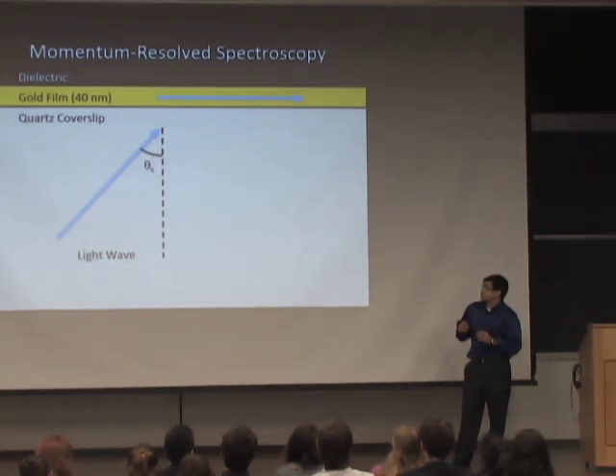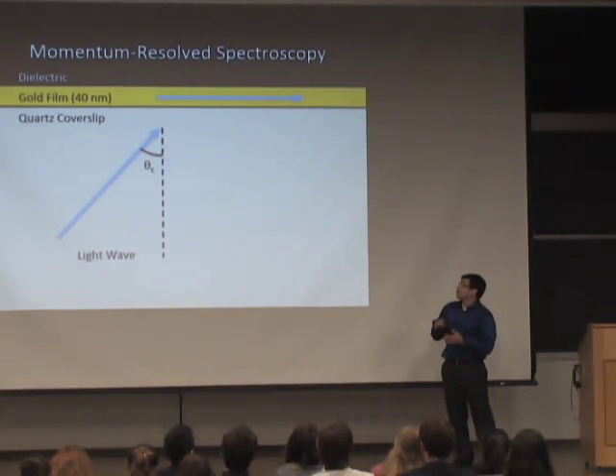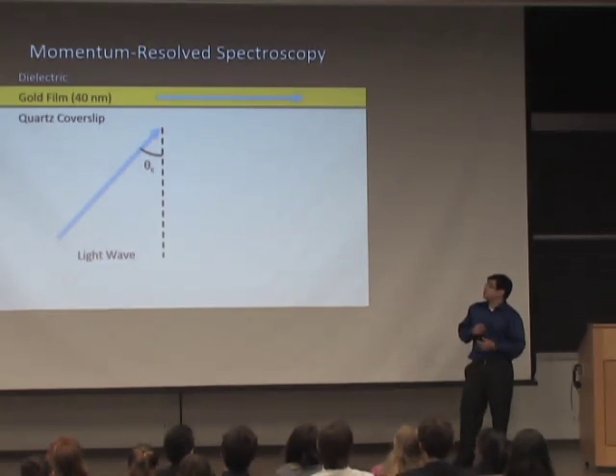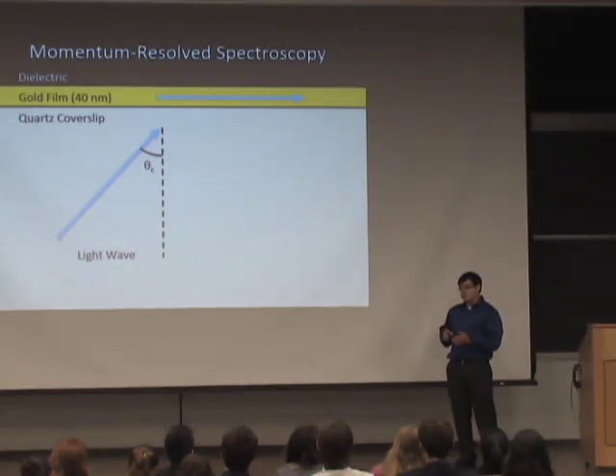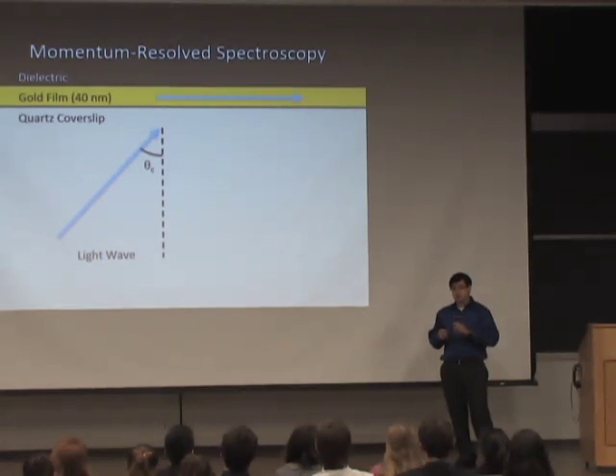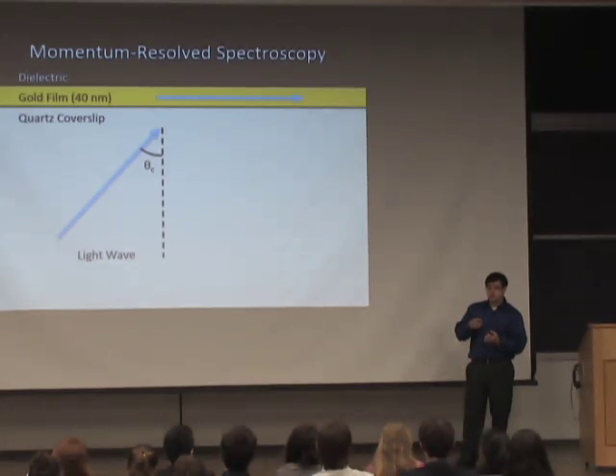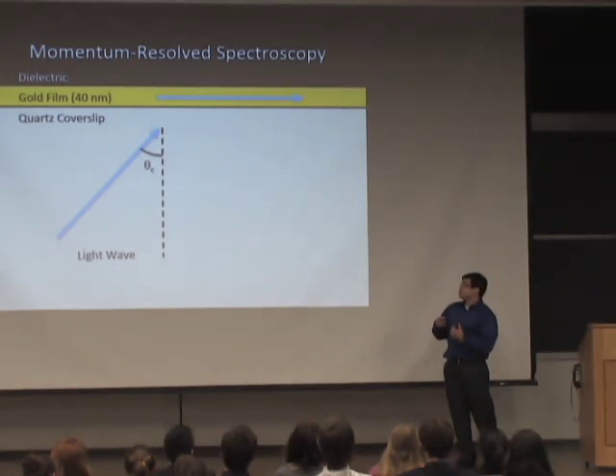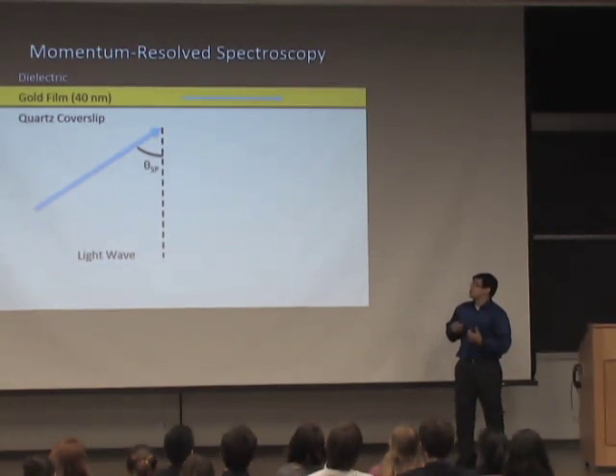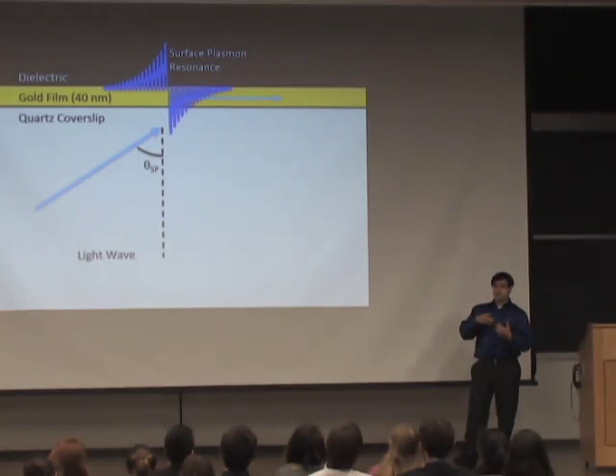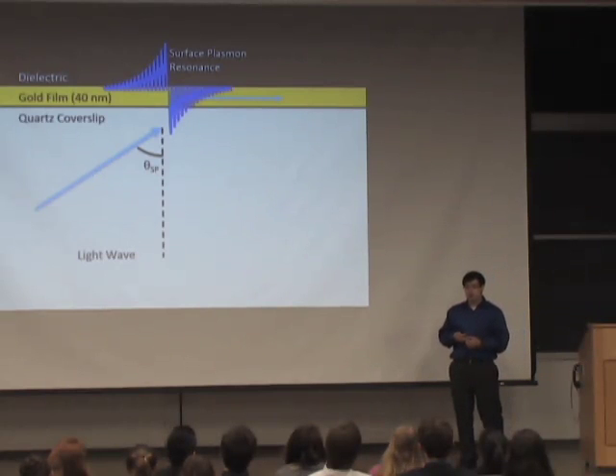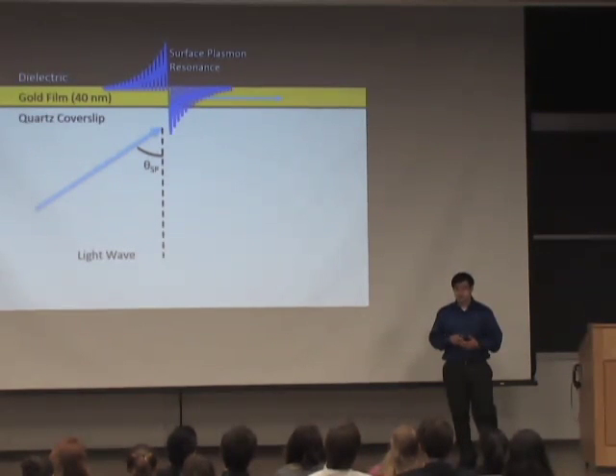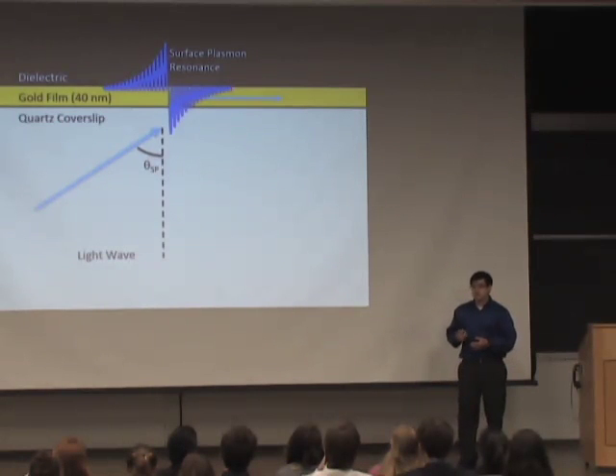And at a point called the critical angle, all the light is reflected and travels along the gold film interface. And what that light wave in the gold is doing is the electric field is exciting little oscillations in the charges in the gold film. Now these charges by themselves, without light exciting oscillations, have a natural oscillation. So if we tweak this angle even more, we can reach a phenomenological point called the surface plasmon resonance, where the electric field matches with the natural oscillations and excites very large resonant oscillations.